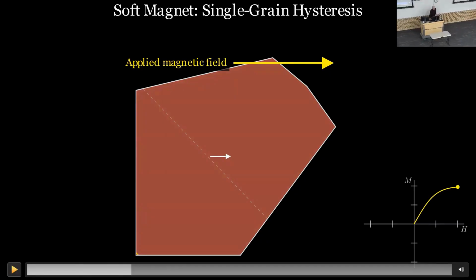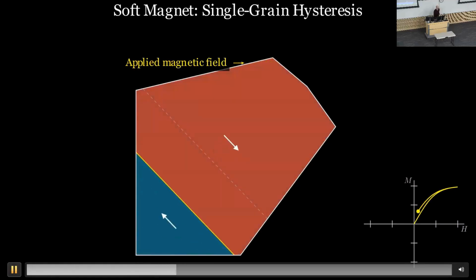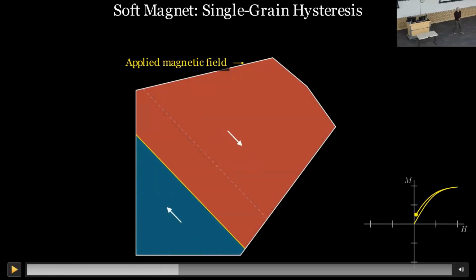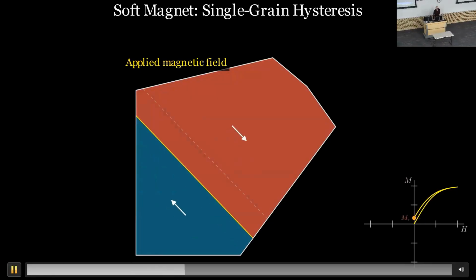Right? And then what we'll do is slowly decrease the strength of that applied field. And remember, the physics wants to demagnetize the material. So the blue region will come back. But usually, in most materials, it doesn't go back to where it started from. That little dotted line shows you where it was when it was demagnetized, right? If I let it go to 0 applied external field, it usually stops a little bit short. See, the red region is bigger than where we started. And you'll see that there's no longer any yellow arrow.